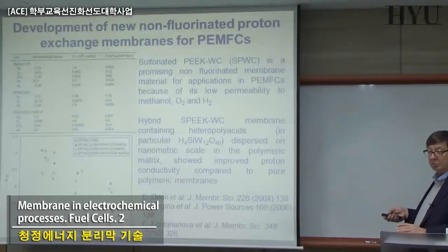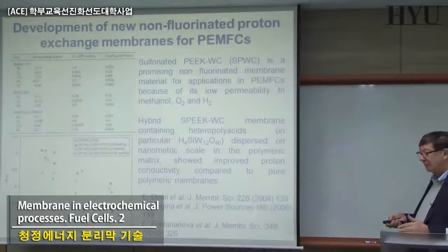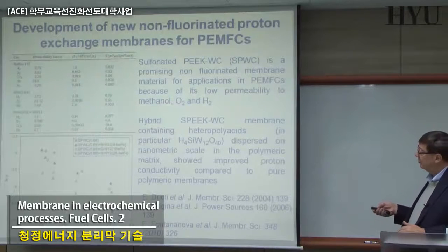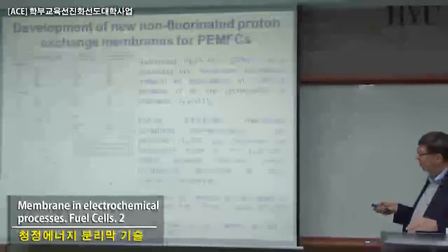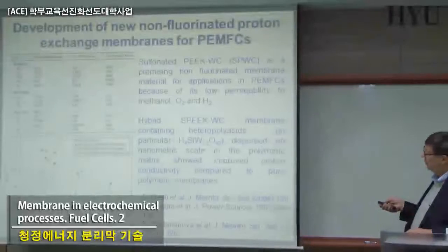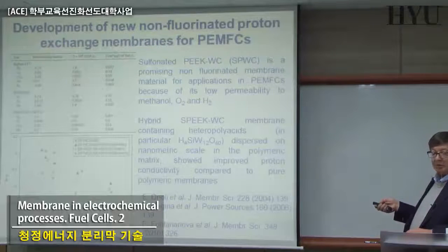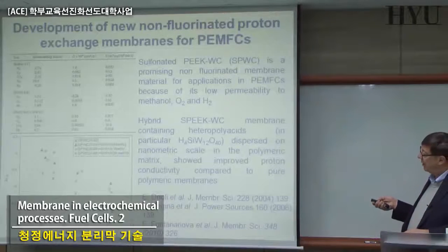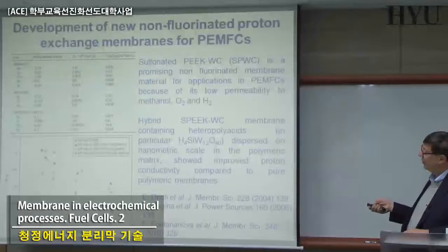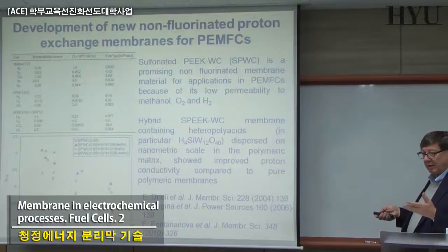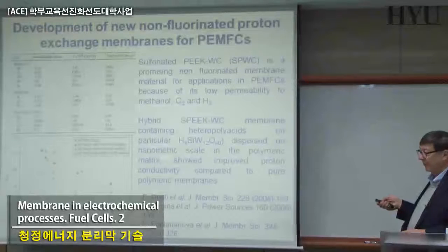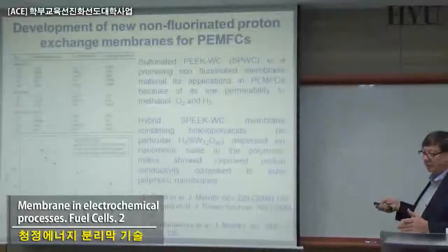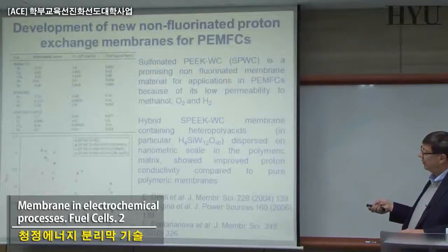What we have been trying to do, with some success, not yet competitive for sure, is to increase this proton conductivity, not necessarily with Nafion at all, by making some hybrid matrix membranes based on this PEEK, combined with some heteropolyacid, materials with very high superacidity, basically. This is typical case one.